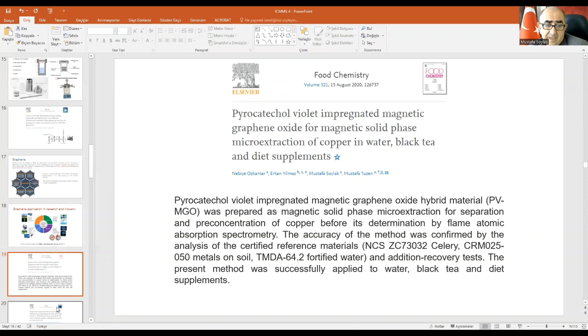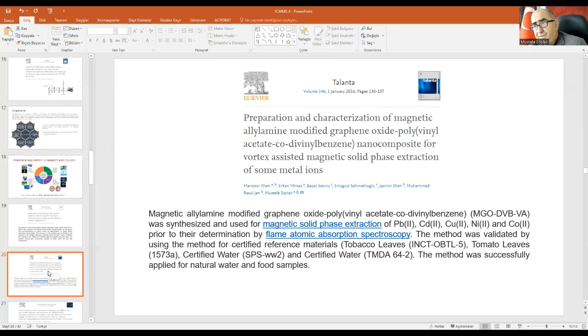Also, another application of these materials is a hybrid material, which is a magnetic allylamine modified graphene oxide plus polyvinyl acetate co-divinyl benzene nanocomposite. We synthesized these materials. Then after characterization, we used these materials for the solid phase extraction of some metal ions.